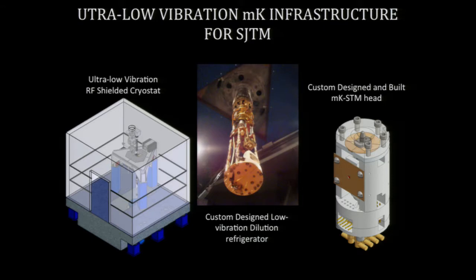This is a floating room where you have a 30-ton block of concrete sitting on 6 air springs, and you have an acoustic room here, and then there's actually another acoustic room on the outside. On the inside, you have this massive tripod, which is several tons by itself, sitting on air springs. You cool the whole thing on this custom-designed millikelvin dilution refrigerator. And by the time you get down to where the tip is, the mean motion of the tip per root Hertz is in the tens of femtometers. So you have a very stable tip where you can form the junction, take your measurement, and then move over and take another measurement.